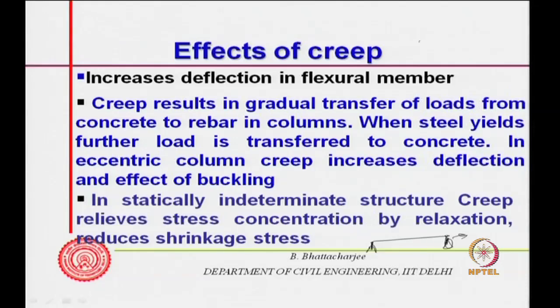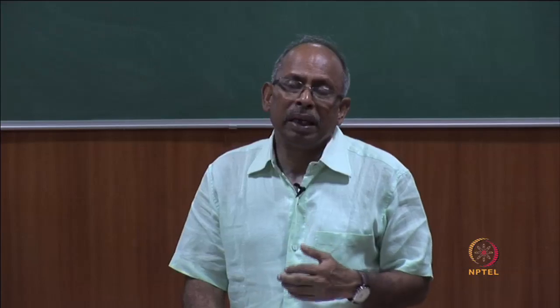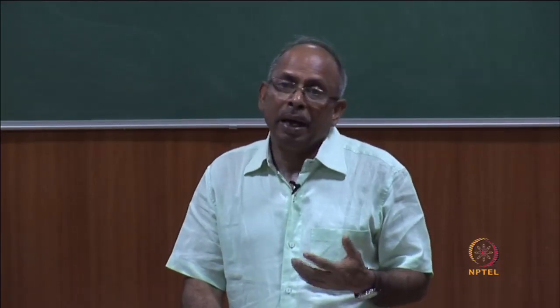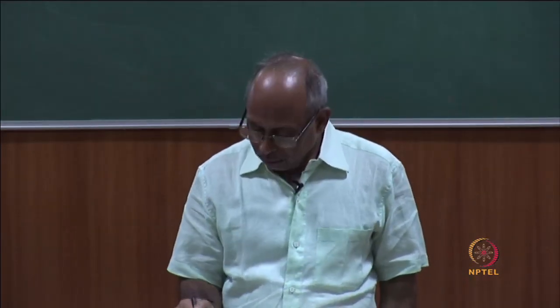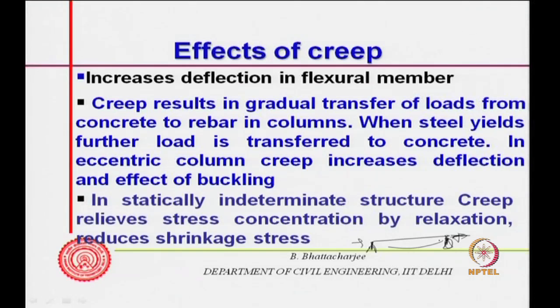So basically creep would have caused some sort of deformation, but then this is restrained, no movement can occur. So this horizontal movement, additionally you will have additional force coming in. So this will neutralize the effect of the applied stress, I mean this is just an example, and relaxation will reduce the stress concentration. Also shrinkage stresses get reduced. For example, if you have shrinkage stress in a restrained element, shrinkage cracks would be tensile, because its natural position is here, after shrinkage it will shorten, we will discuss shrinkage later on, but the shrunk position is somewhere there, but it is restrained.